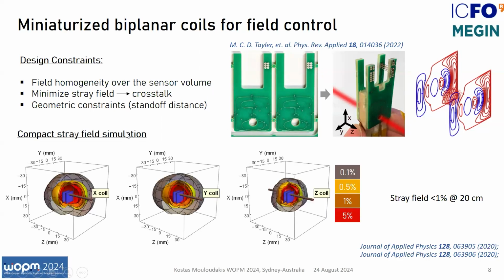We have performed simulations, but also measurements, both of the field homogeneity and the stray field. And we find that the stray field along all X, Y, Z directions is below 1% at a distance of 20 centimeters away from the sensor.